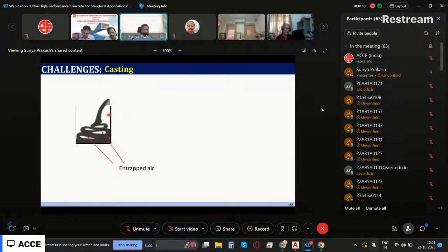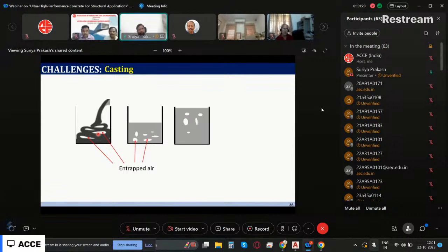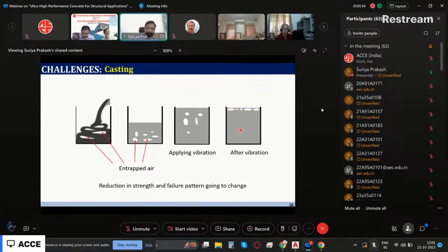Now, during casting, you can entrap air. Though it is self-consolidating concrete, you can have entrapped air there. And when you do vibration, these voids will come to the surface, and that is usually the reason the outside, top surface will always have less strength compared to the internal concrete. So there is a reduction in strength, and the failure pattern is also going to change.